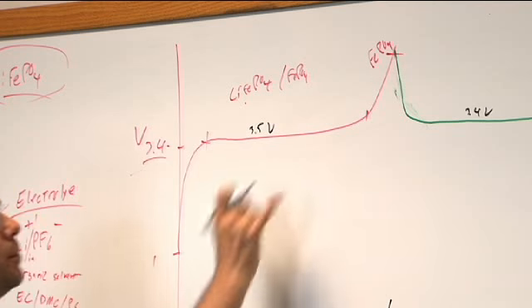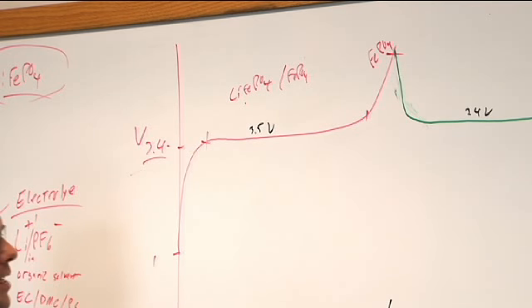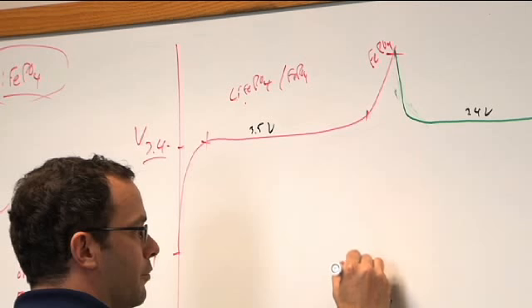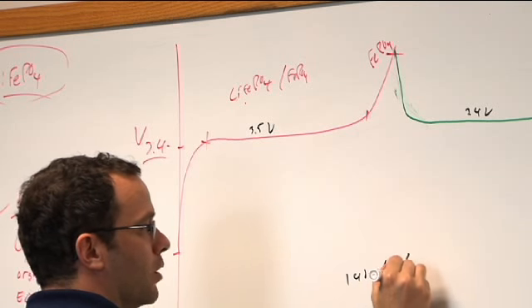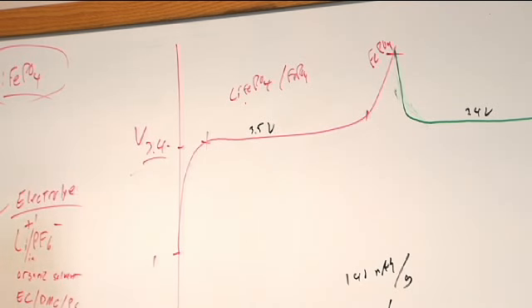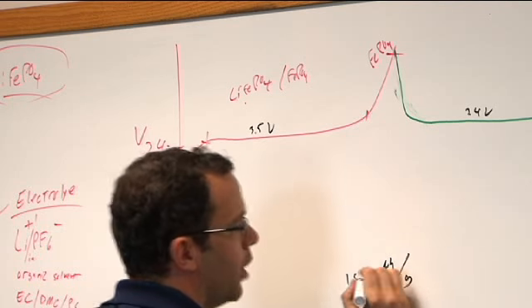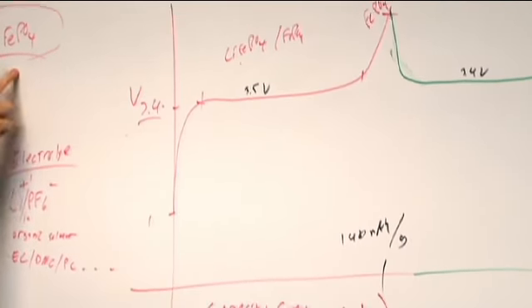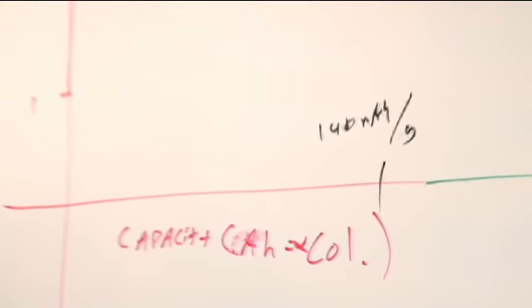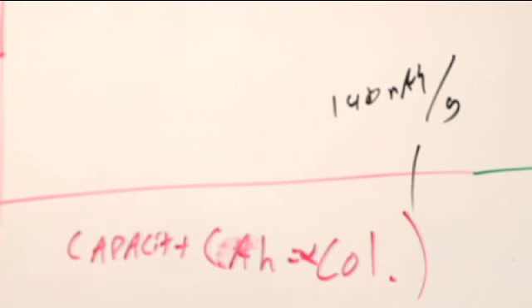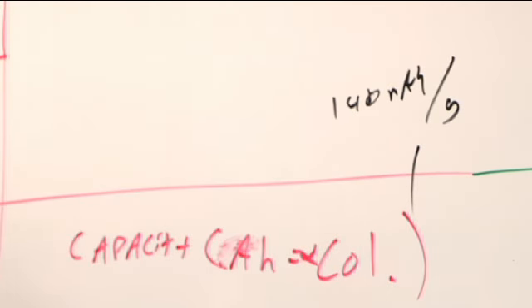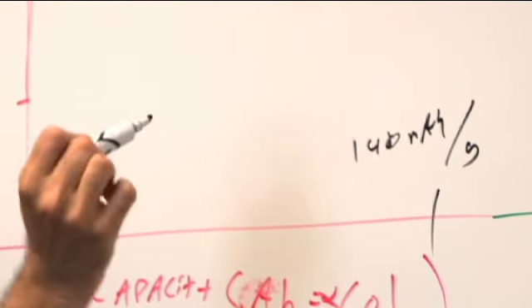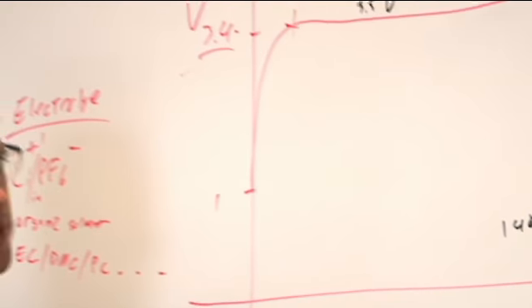And the capacity we'd expect from a lithium iron phosphate based system is something like 140 milliamp hours per gram of lithium iron phosphate. If you ever wonder how much active material you actually have in your materials, you can say, well, I have this many amp hours. You can back calculate using roughly 140 milliamp hours per gram of specific capacity, and figure out, well, I probably have that many grams. So for every gram of lithium iron phosphate you put in the system, you can expect to get about 140 milliamp hours of charge capacity and discharge capacity.